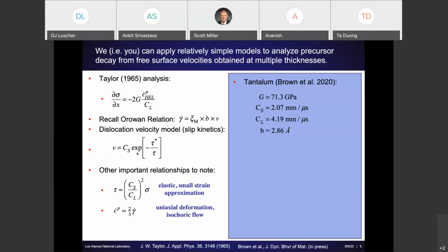If you could visualize what this curve is, which is actually the first thing I asked you to do, you would see that it's going to limit out at this shear wave speed. That means the dislocation, under the highest stresses, will move at a rate of about 2 millimeters every microsecond through our material. And then I said there are some other closure relationships you would need to solve the problem. One is the relation between this axial stress sigma, which is what our differential equation is expressed in terms of, and the shearing stress that's moving the dislocation.